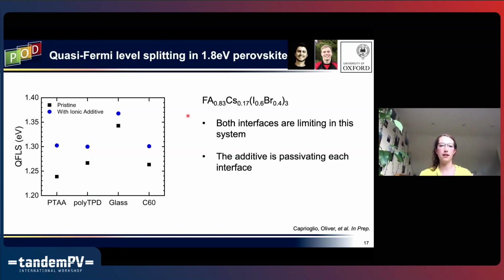And so looking at analyzing where these VOC gains are coming from, we use PLQY to calculate the quasi-Fermi level splitting that we see in the films. In this case, we have just the neat perovskite on glass, and then also with the charge selective contact layers, as you can see here, and then with and without the ionic additive. So we get a bit of a boost in the PLQY, or better quasi-Fermi level splitting with the ionic additive.